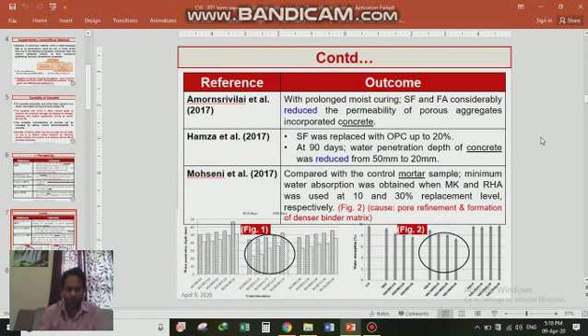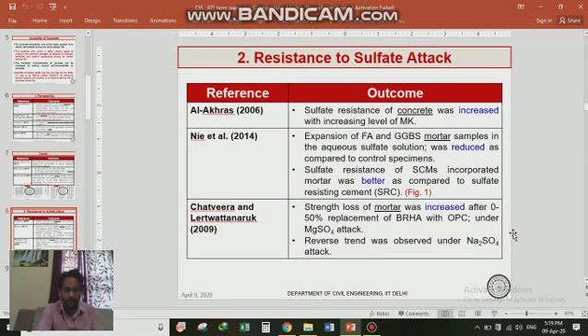So here we can see that metakaolin and RHA impart lower water absorption as compared to the other mixes. Further, regarding resistance to sulfate attack, in 2006, Al-Akhras studied the sulfate resistance of concrete, and it was concluded that it increased with the increasing level of metakaolin, due to the high fineness of metakaolin as compared to OPC. It acts as a pozzolanic material, which increases the packing density, and pore refinement takes place.